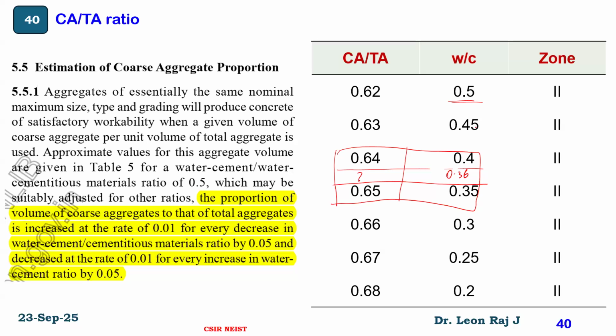So for every decrease of 0.05, there will be an increase of 0.01 value of CA by TA value. For every decrease of 0.05 in water cement ratio, there will be an increase of CA by TA of 0.01. So if the value comes in between, you have to do the interpolation.